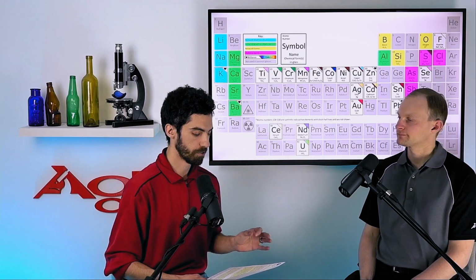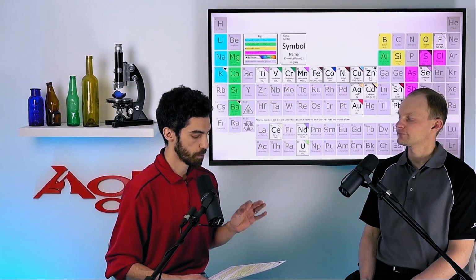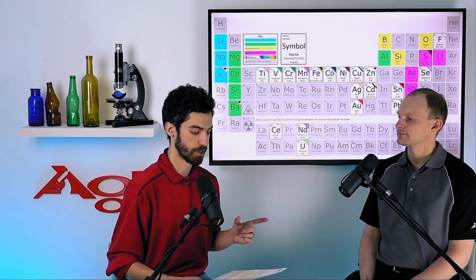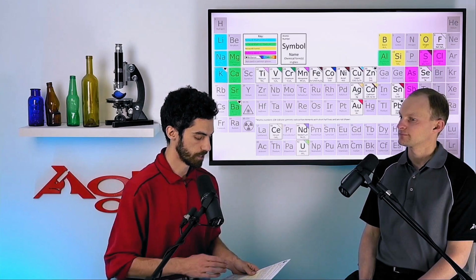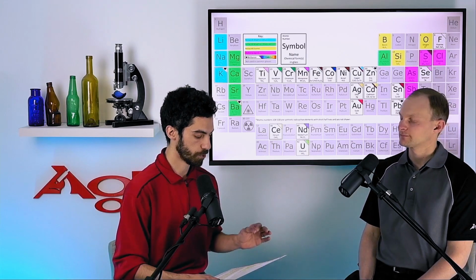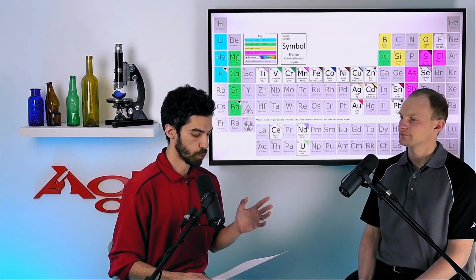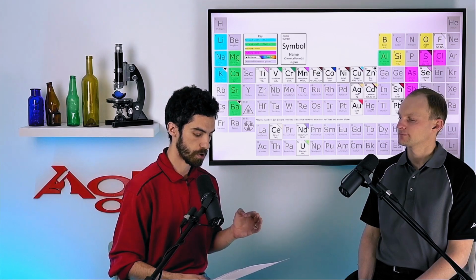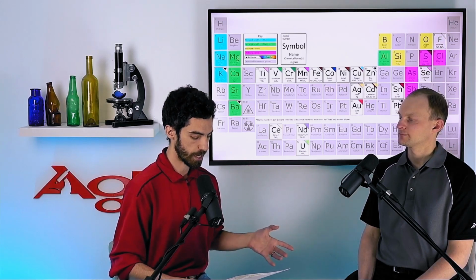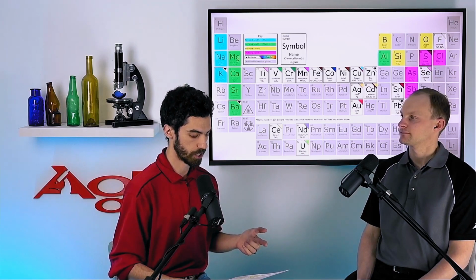So paper can actually be recycled about 5 to 7 times. Plastic, only 2 to 3. Now, metals, such as aluminum cans, and glass, those in particular, can be recycled infinitely. So why the stark difference? Now, he says here, according to the professor of environmental history, Finn Jorgensen, as the paper is broken down or recycled, the fibers get shorter and less flexible. That is more or less true for plastic as well, as its chemical composition changes during reprocessing, thereby decreasing quality. Metals and glass, on the other hand, can be melted down and remolded into the same high-quality product that was recycled. So that's fascinating, right?